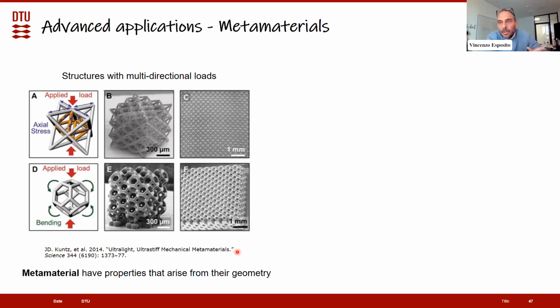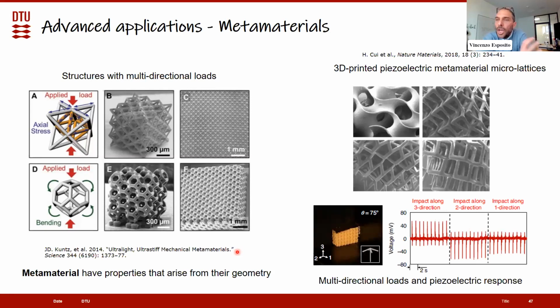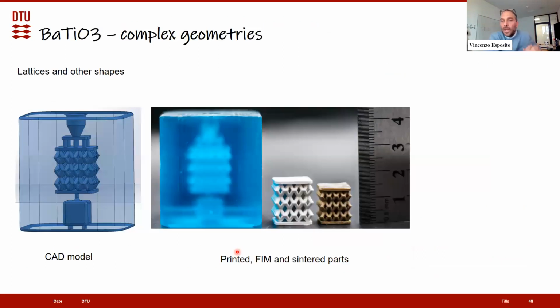Metamaterials are materials that have properties that arise from the geometry, and they go beyond the properties of the material itself. This is, of course, very well known for mechanical systems and optical systems, but somehow these systems are, let's say, passive. They don't have intrinsic properties. We start seeing a change in the literature when it comes to metamaterials with active components, especially with piezoelectrics, especially when it comes to energy harvesting, or composites. This Nature Materials paper is an example of polymers loaded with piezoelectric powders that can be used for energy harvesting. And we have tried that. We have tried to make superlattices with our freeform injection molding, and this is one of the results.